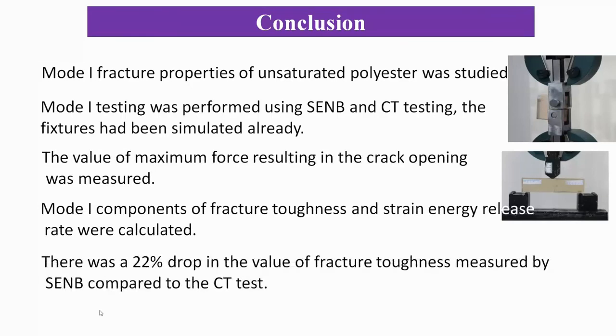There was a 22% drop in the value of fracture toughness measured by SENB compared to the CT test specimens. This could be due to factors such as out-of-plane load in the CT test. However, if we take the standard deviation of the results, we see very close values obtained from both tests.